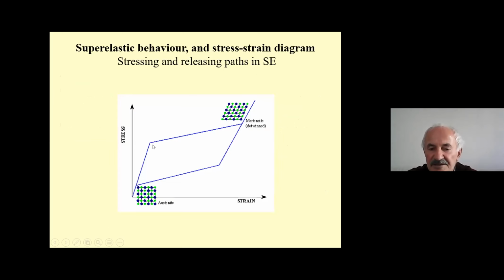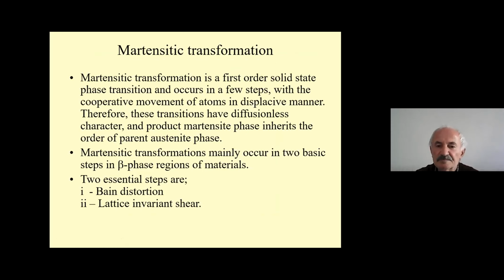This is the stressing and releasing diagram in superelasticity. As you can see, stressing and releasing paths are different, and this slope refers to the energy dissipation. By the stressing, ordered parent phase structures turn into detwinned martensitic structures by means of stress-induced martensitic transformations.